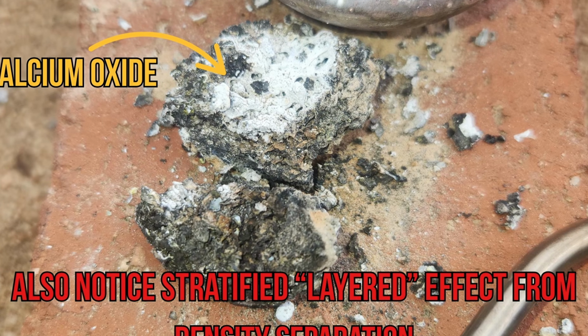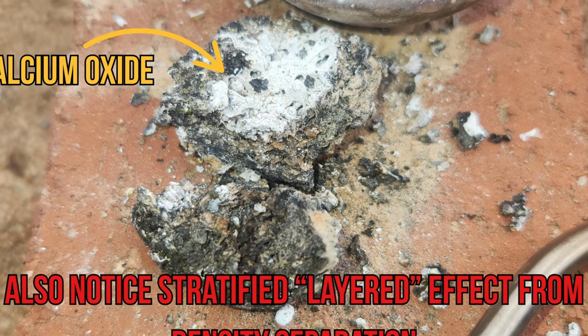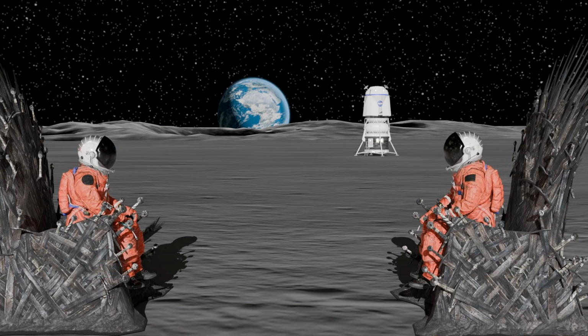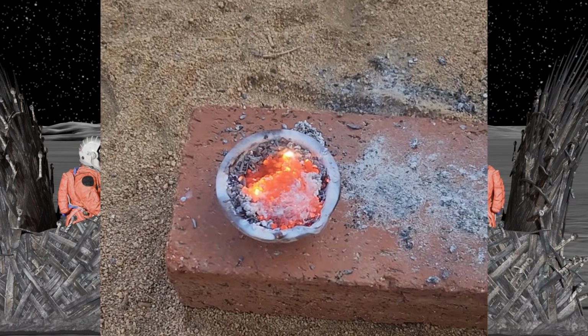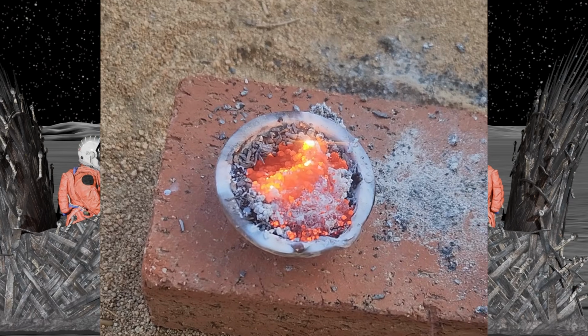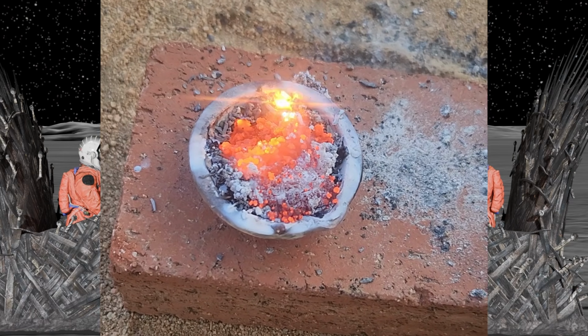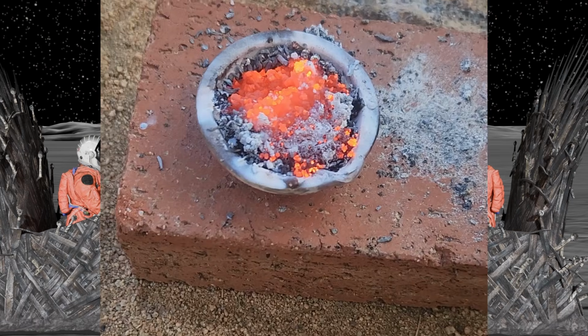That's also because the simulant itself was not beneficiated. Had we done it with beneficiated simulant, where we had removed the iron and removed the silica, then yes, the reaction would favor the oxygen bound to the regolith, as opposed to the oxygen in the atmosphere. And this process is going to happen with some kind of pressure. It's going to be extremely low pressure, but the process itself is going to release outgassing, which is going to create some type of pressure. So there needs to be some more experimentation on that as well.